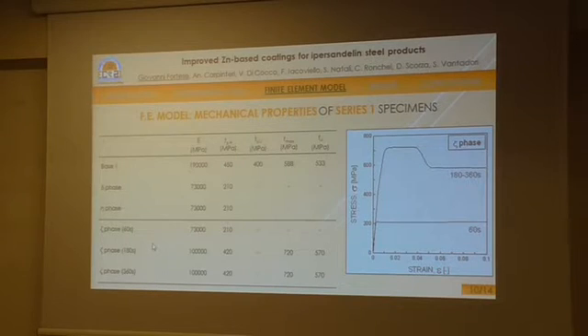The mechanical properties of series 1 specimens are listed in the table in terms of elastic modulus, high and low yield stress, tensile and ultimate resistance. In particular, the stress and strain curve related to base 1 corresponds to that of ductile steel, whereas elastic plastic behavior is assumed for both delta and theta phase.